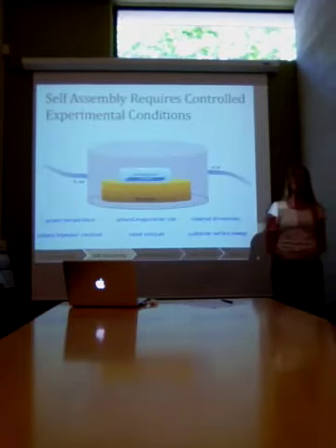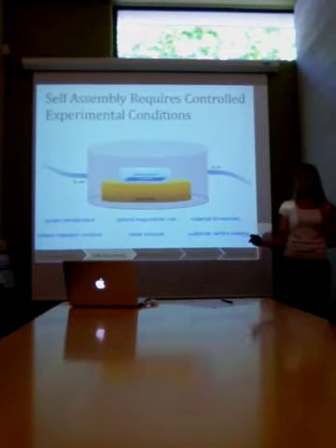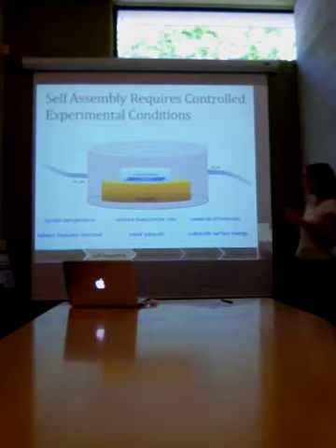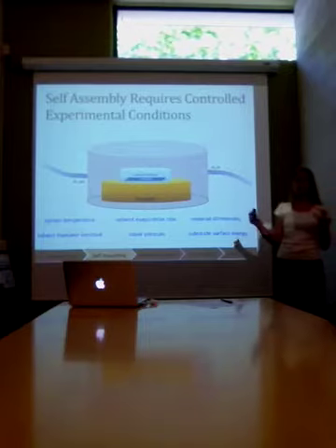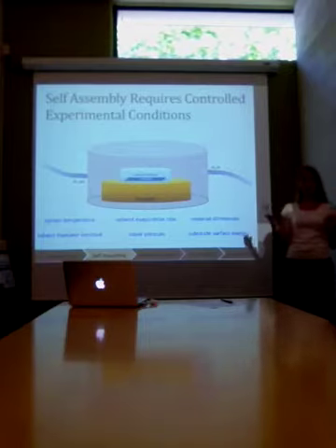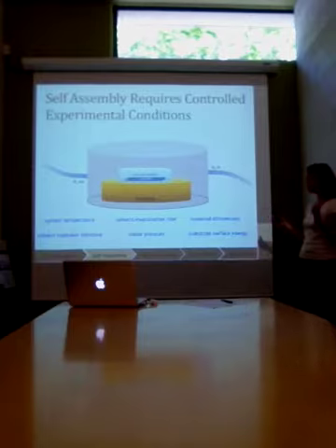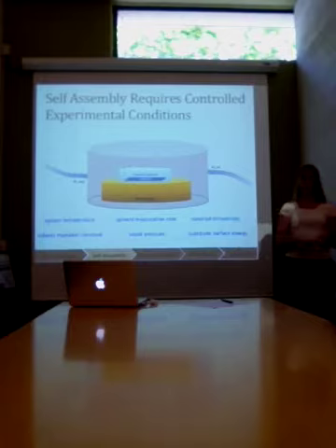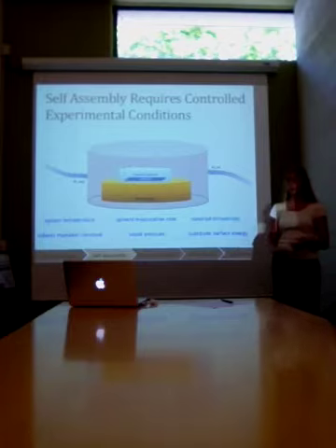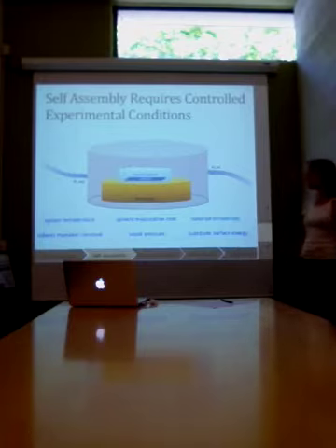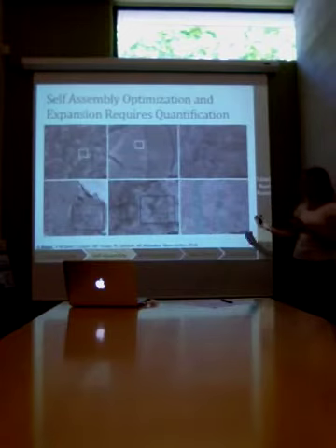So to get the nanorods to align experimentally, we needed to be able to control this parameter space. First, we needed to engineer a system that would independently control the temperature of the system and the vapor pressure, or the evaporation rate. We also needed to select appropriately the substrate, the solvent, the nanocrystals, and their ligands. And if we got all those parameters right, as I said before, we could see nanorod alignment.